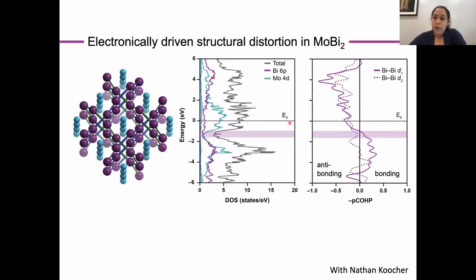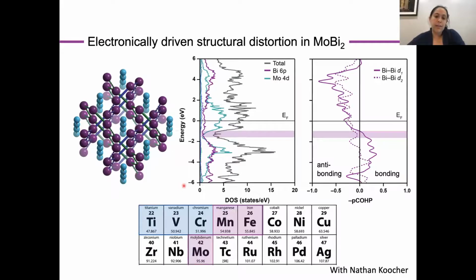One of which is that we would expect the greatest amount of distortion to occur when the Fermi energy and the pseudogap coincide, in which case we're occupying the least amount of antibonding states. That's equivalent to taking electrons out of the system or moving to the left on the periodic table. And that helps to explain why the titanium bismuthide version of the structure is the most distorted. And indeed, when we look at the density of states for that structure, the Fermi energy almost exactly coincides with that minimum in the density of states.